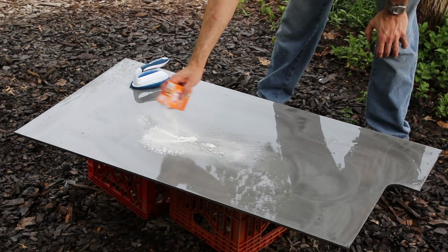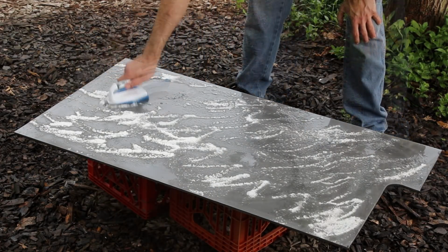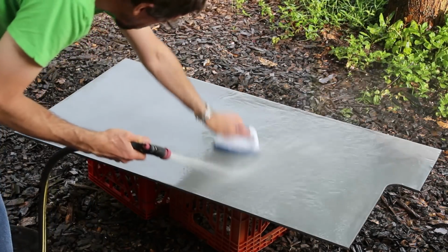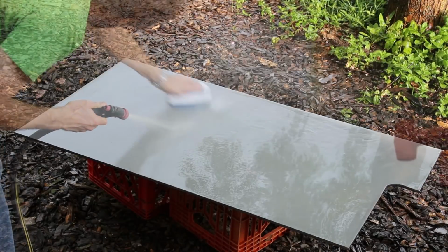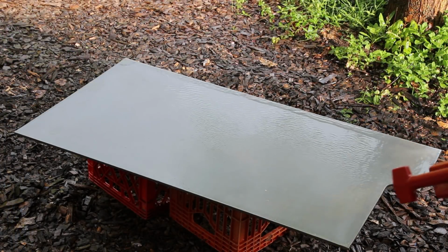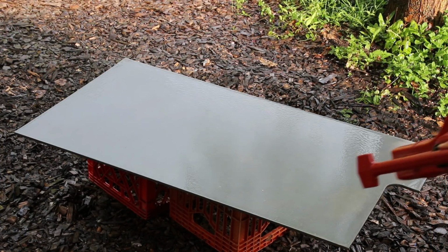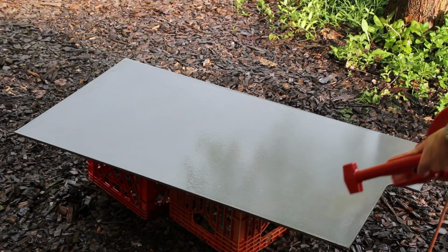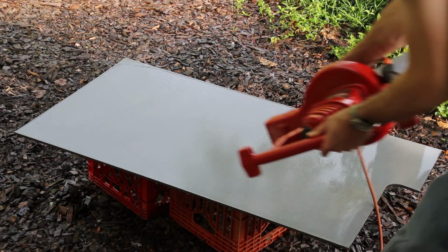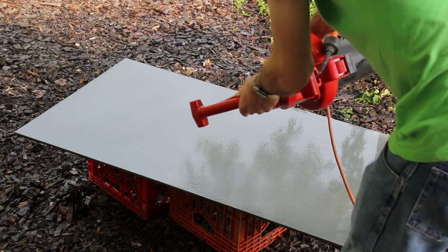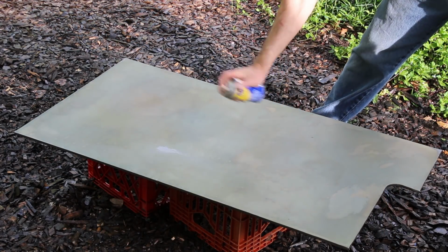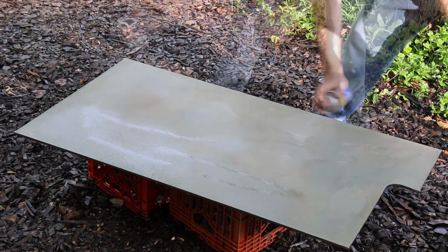I'm going to neutralize the acid with baking soda, and once it's pretty well neutralized, wash the whole surface down with water, get it nice and clean, and then I'm going to use my leaf blower to quickly blow dry the entire surface as quickly as I can, because if it's left damp it rusts very quickly. And then as soon as it's dry, spray it down with WD-40 and wipe that in real well.